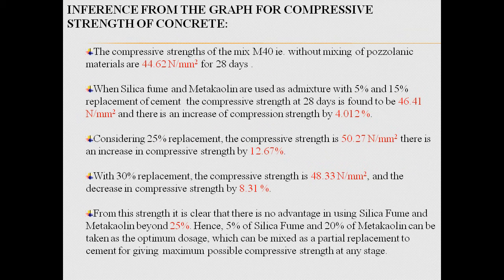The maximum is obtained for M40 without mixing pozzolanic material, it is 44.62, and when silica fume and metakaolin are admixed at 5 and 15, it is 46, where there is an increase of compressive strength of 4.012 when compared with conventional concrete, and at 25% replacement, that is 50.27. This is the maximum one, where the compressive strength is increased by 12.67. So 5-20 can be taken as an optimum dosage, which can be mixed as a partial replacement.